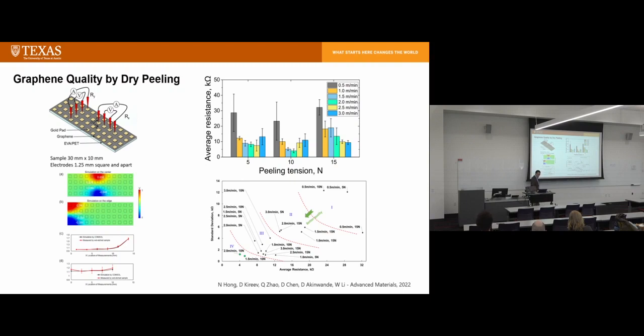So first of all, for graphene quality, especially on this large sheet, or comparatively large sheet, 10 millimeter by 30 millimeter, we want to measure the surface conductivity and also the uniformity of transfer quality. It turns out measuring conductivity of graphene on surface is not that easy because the resistance is relatively high. So we made an array of gold electrodes on the surface, and those gold pads are 1.25 millimeter by 1.25 millimeter square, and the gap among the electrodes is also 1.25 millimeter. And we use 4-probe method to measure the conductivity.